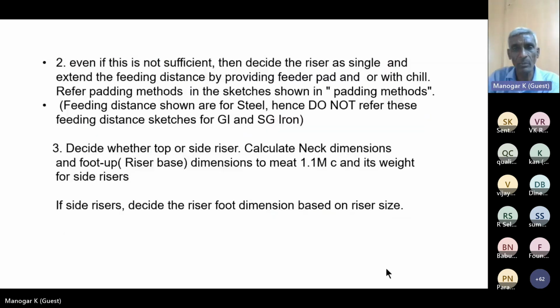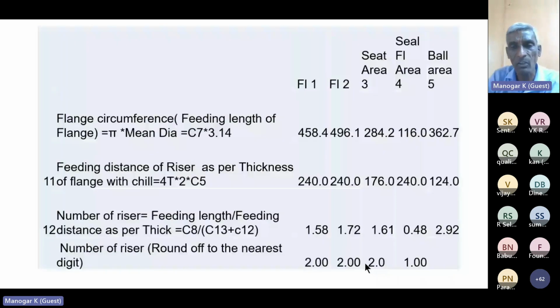So feeding distance can be increased by adding padding or chills. The padding methods will be shown in the last sketch. And decide whether it is a side riser or top riser. If it is a side riser, then you have to calculate the neck contact modulus, which should be 1.1 times the modulus of casting. The side riser will have a foot pad to keep the riser. Then the foot pad weight also has to be considered along with the casting weight for the riser to feed.